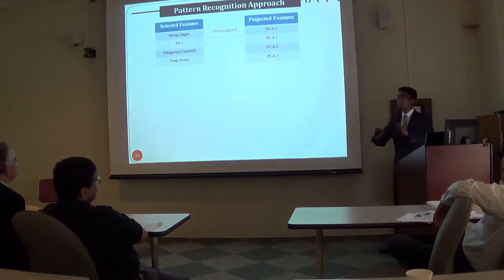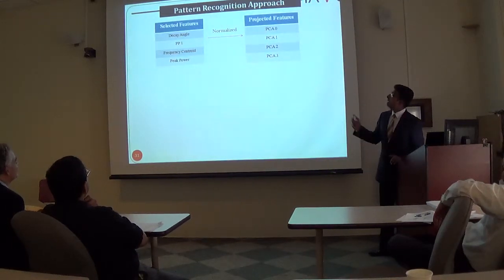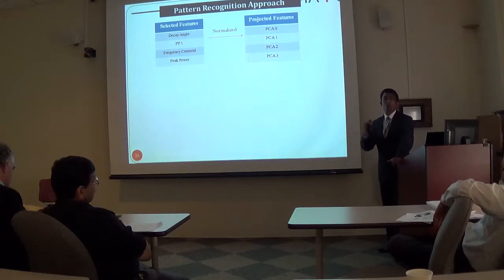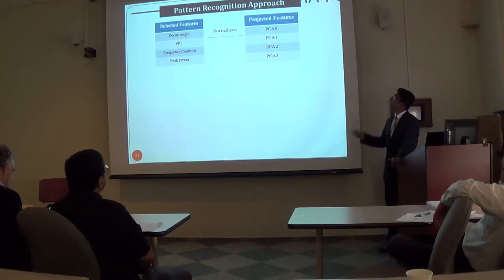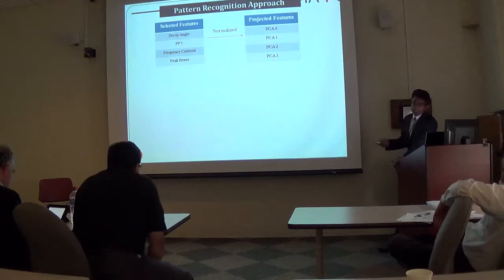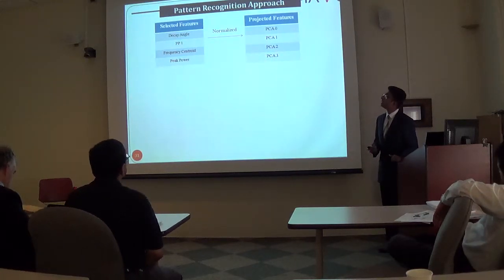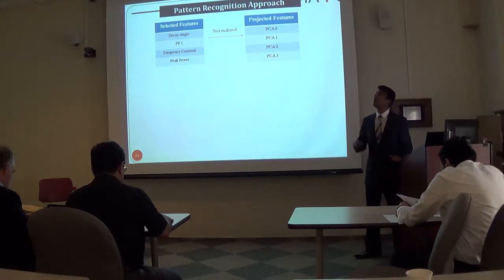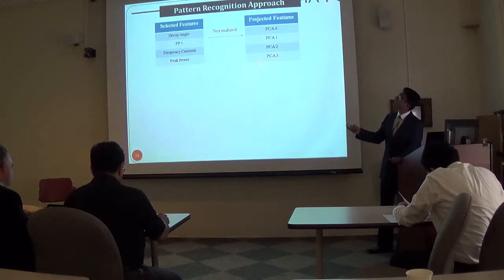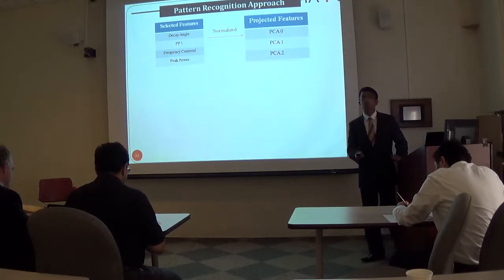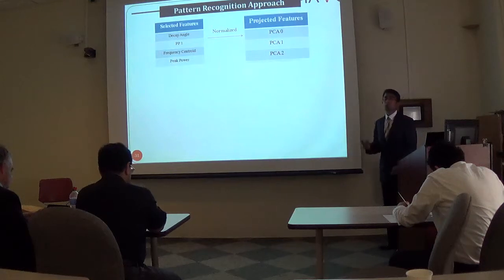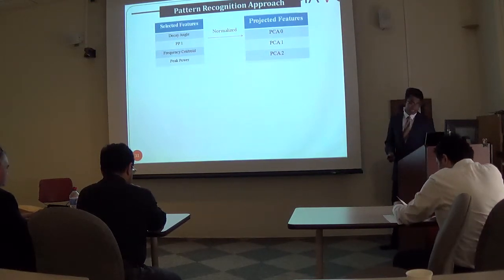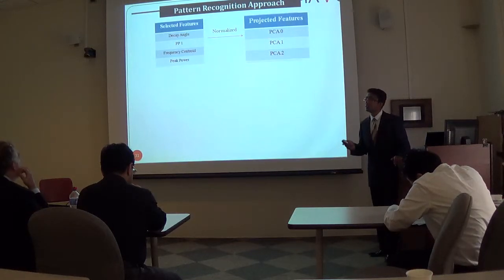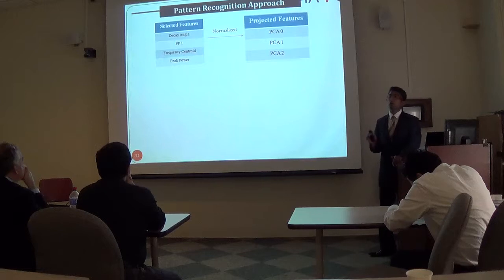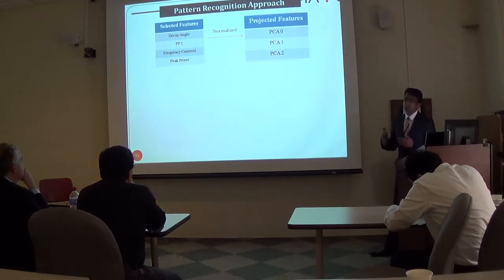Now, in order to classify and separate the AE signals that were obtained during the fatigue testing, pattern recognition algorithms were applied to separate them into several different classes, and potentially associate all these different classes with certain sources. So 4 different AE features were utilized, such as the decay angle, the partial power 1, the frequency centroid, and the peak power. These features were then normalized and transformed to the orthogonal basis using principal component analysis as shown here. Only the first 3 principal components were utilized as these vectors constituted 90% of the AE data in the test. Subsequently, statistical pattern recognition algorithms were implemented, and specifically the k-means algorithm was implemented to classify and separate the different AE signals into several classes.